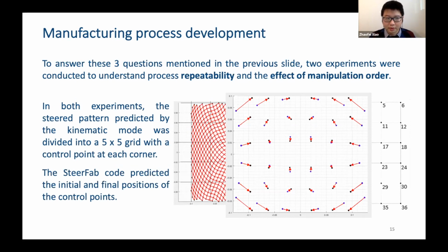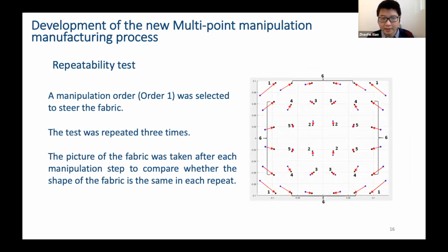Then we use the SteerFab code to predict the initial and final position of those control points. So in the repeatability test, we designed a manipulation order, in which the numbers on this figure show the manipulation sequence. This test was repeated 3 times, and we took a picture after each manipulation step to compare the fabric shape at each repeat.